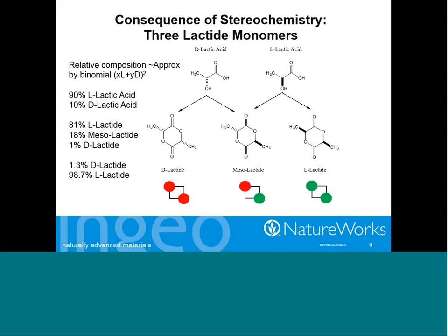So as an example here, a lactic acid stream that's 90% L-lactic acid that's fed through our process of oligomerization and then on to making lactide would produce a stream that's about 81% L-lactide, 18% mesolactide, and 1% D-lactide. Now, as I mentioned earlier, the L and the D-lactide are enantiomers, so those we cannot separate. But if from this stream we were to remove all of the mesolactide, we would end up with a stream that would contain 1.3 weight percent D-lactide and 98.7% L-lactide. So, via this distillation process, we could produce a lactide stream from this example with anywhere between, let's say 0 and 18% mesolactide.